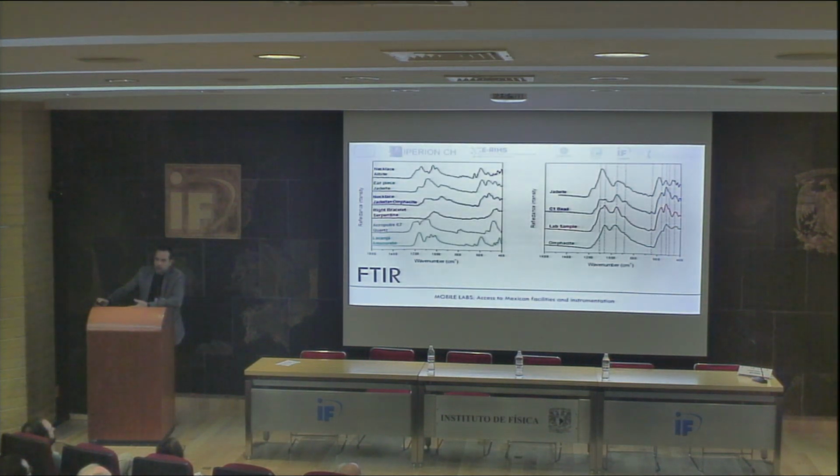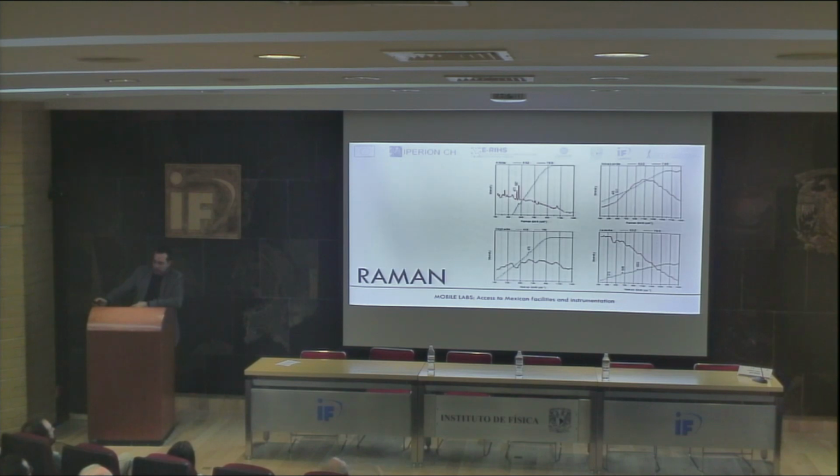So with infrared spectroscopy, we were able to identify the main minerals, and we identified a lot of them actually, and we could even identify a mix of jadeite and amphibole in some beads. With Raman, we confirmed some of these findings. We found that for greenstones, it's much better to use the 532 line of the laser, even though we could have some very good spectra with the red laser, but it's not so common. Usually you get only fluorescence.